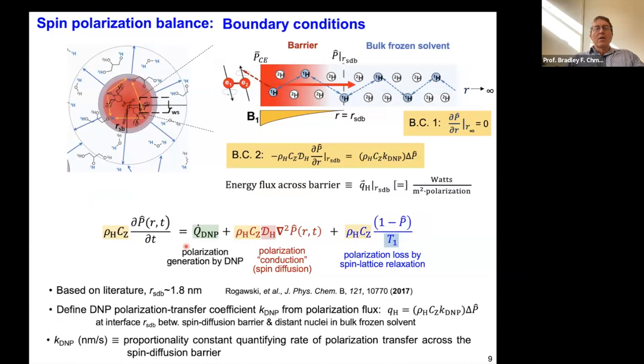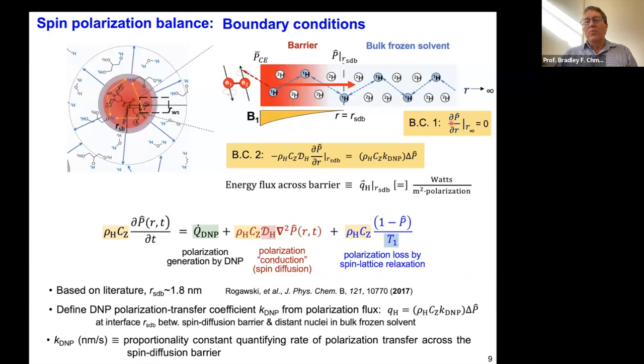In many cases you need to know the spin diffusivity in order to make it essentially adjustable-parameter-free. We also have an experimentally imposed generation term — basically the source we're applying with our continuous microwave spins. So now with that, we can say this looks like a second-order partial differential equation, and we can impose boundary conditions. We need two spatial boundary conditions.